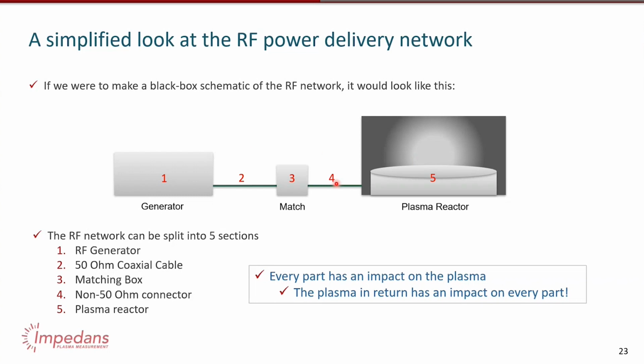In terms of going deeper than that, so for example, what specific component is causing the issue? That is possible. At the end of the presentation here, I was going into harmonic generation, and I deleted a whole bunch of slides because I knew we'd run out of time. But the harmonics tend to react uniquely depending on the part that is causing the problem. So we've done experiments on a tool where we had a VI probe there, and over a period of a day or two, basically induced faults on the tool. Like add in nitrogen to simulate an air leak, make it so that wafers are not sitting correctly, make it so the shower head is blocked, make it so an MFC doesn't open on time, and so on.